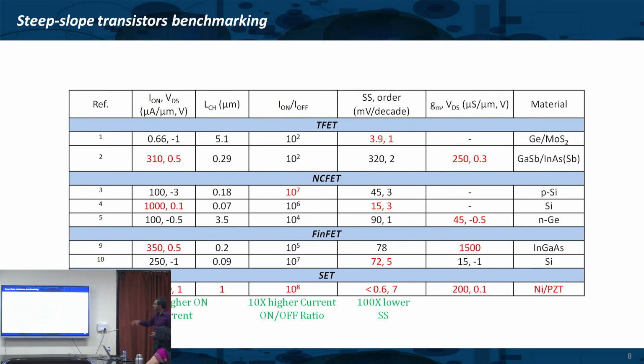And here I am comparing with TFETs. You see, these are the numbers that people have achieved: 3.9 millivolts per decade. This is NCFET, negative capacitance FETs. This is typical for MOSFETs, not 60, more, because there are a lot of non-idealities. And look where we can get. We can go down to even like 0.6 millivolts per decade, so 600 microvolts, okay, because it is just the perfect switch that you can make, right, just by doing this cracking process, with very simple material, nickel and PZT. You can also do it with graphene, okay.